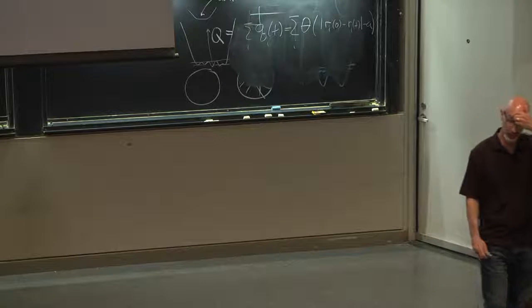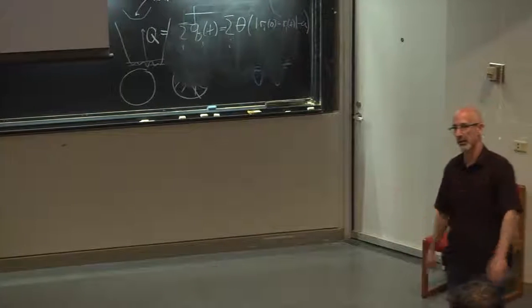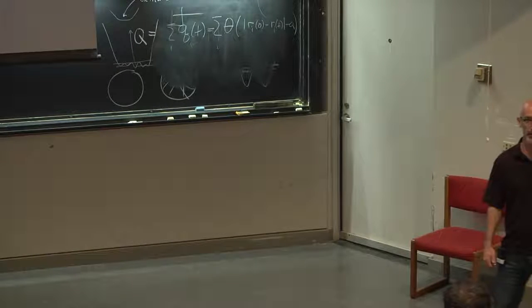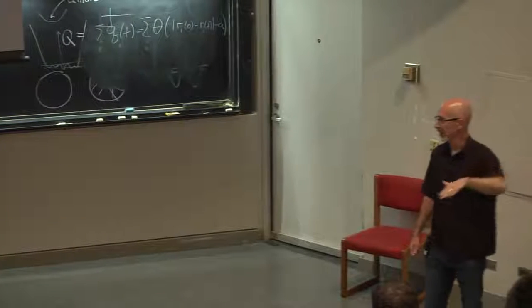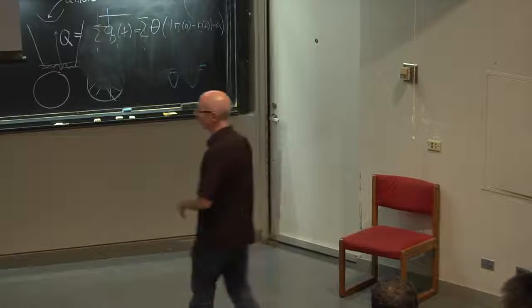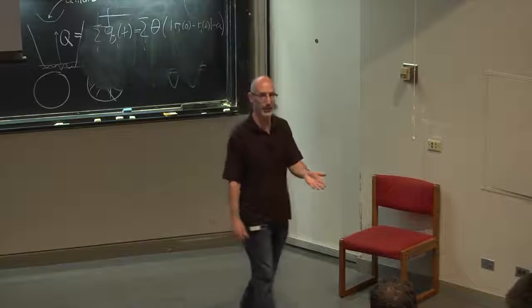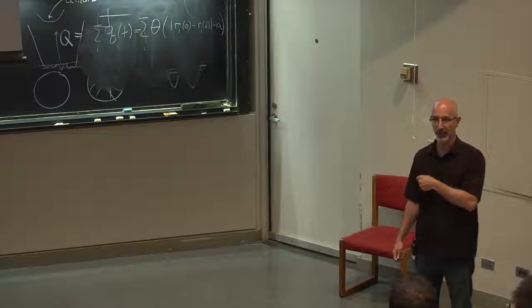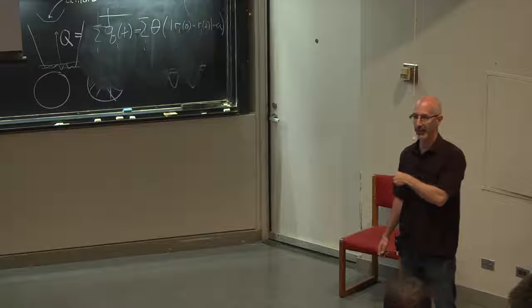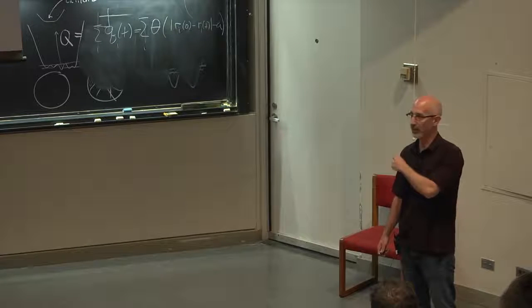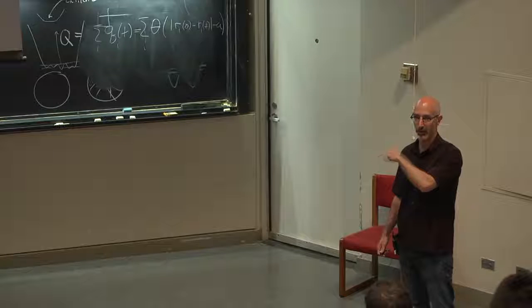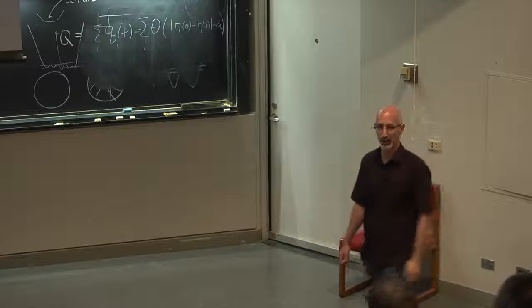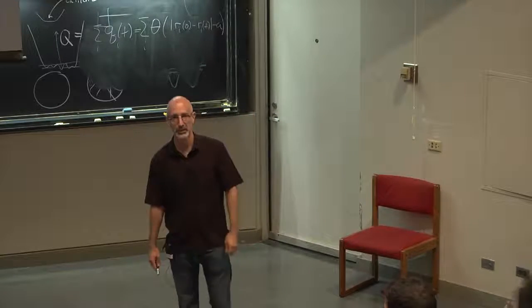And this is what I was mentioning in reference to Jorge's question on liquid. So if you take glycerol or something, you can get an upper bound on what the susceptibility should be near the glass transition from this. And the interesting thing is when you use that bound, if the bound is saturated, it should give you an accurate estimate of the length scale. And what you find are actually quite small length scales, even at TG, which is far below what we can do in the computer. So the question is, how is it possible that my length scale is 5 particle diameters at the dynamical transition, but it's still seemingly either that size or smaller at TG in the experiment?